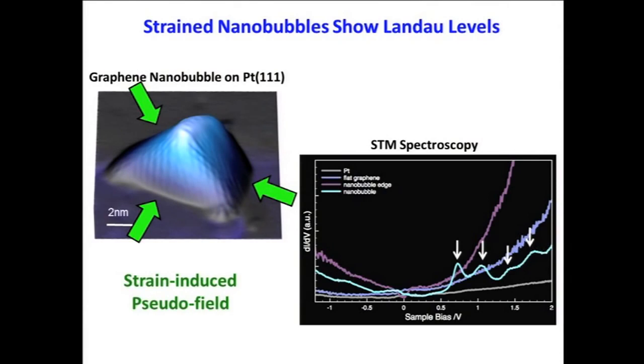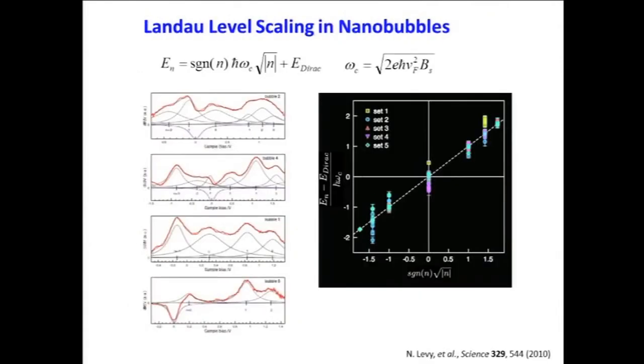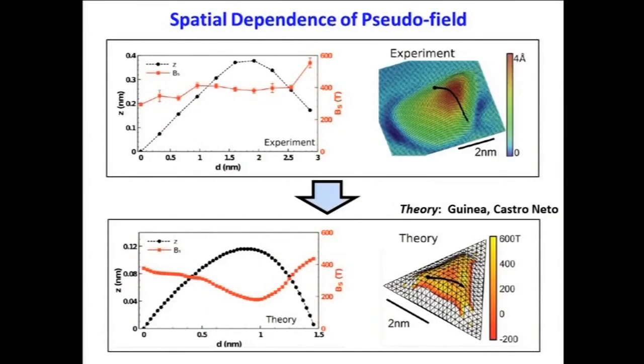In order to further test that idea, we looked at a lot of these nanobubbles. We performed spectroscopy on a lot of them, and we took all of the different peaks and plotted the distribution of peak energies as you see here. And we see that this peak distribution follows the behavior that we would expect for Landau levels in graphene, a square root of n behavior. From this behavior, we can then extract a pseudomagnetic field from the spacing of these peaks. And when we extract that pseudomagnetic field, we get a field that's very high, on the order of several hundred tesla. Here, for example, I show results from one particular nanobubble. Here's a picture of it. And here you can see the pseudomagnetic field that we extracted from this nanobubble, up here at around 400 tesla.